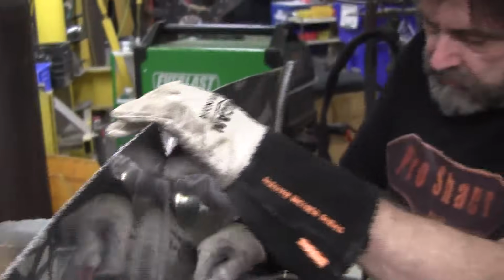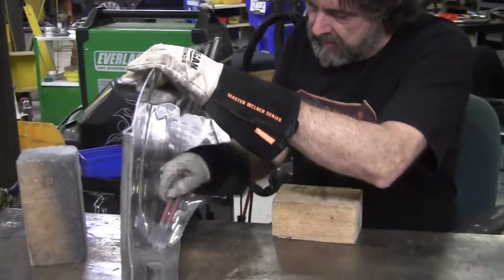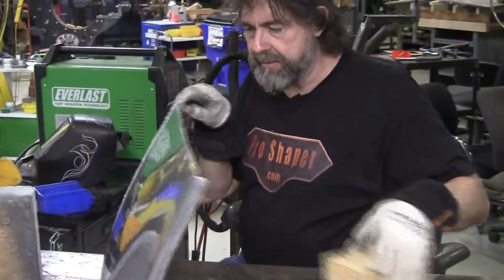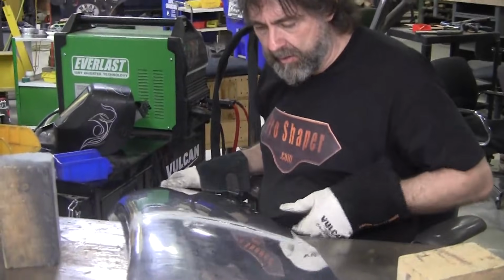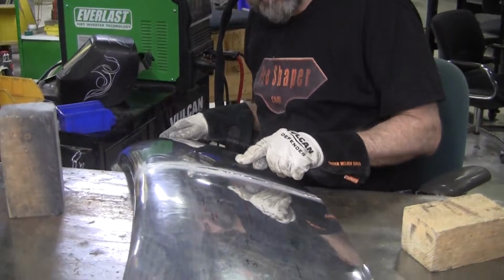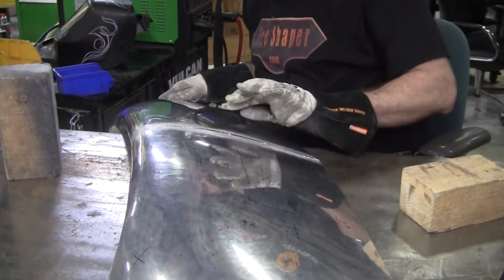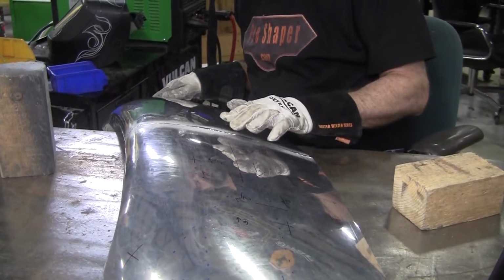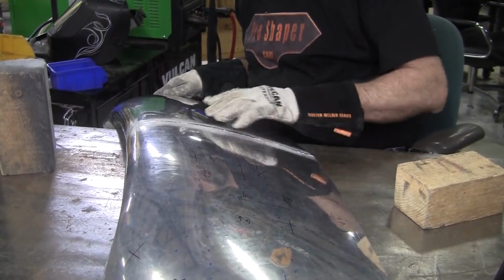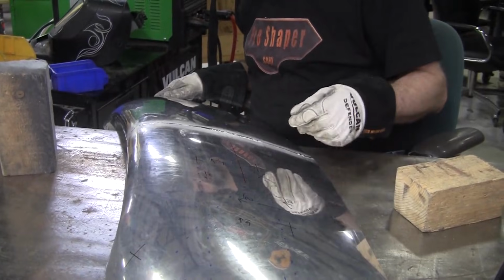And there we have it. The weld is on both sides. Now this weld should be very, very good. You can actually torture a weld like this, meaning grind it and hit it with a ball-peen hammer, and you can raise about an inch blister with a ball-peen hammer before that weld will start to not break, but it'll break adjacent to the weld.